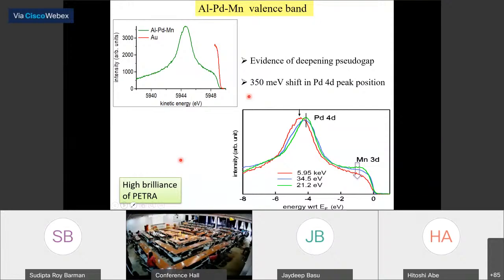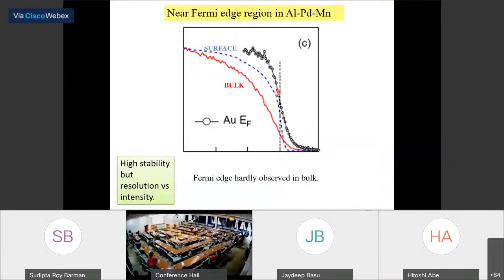Of course, these two are at low photon energies, not done at PETRA, compared to the high photon energy data. You see that as you use the high photon energy, the intensity is coming down. And what is the reason for that? If you look at that particular region, which requires high stability, because this is the bulk photoemission, and if it is shifted from the Fermi level only by a couple of tens of milli electron volts, we need a very stable beamline, and that's why PETRA is also quite useful, because it works in the top-up mode.